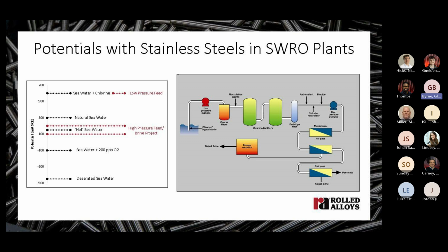We have the permeate water, where typically the chloride content is very low, 250 ppm chloride and less, at a potential of 200 to 100 millivolts. And the brine reject line, which is typically 30 to 40,000 ppm of chlorides, again at 200 to 100 millivolts. So the brine reject pipework and the energy recovery devices see these more severe conditions.